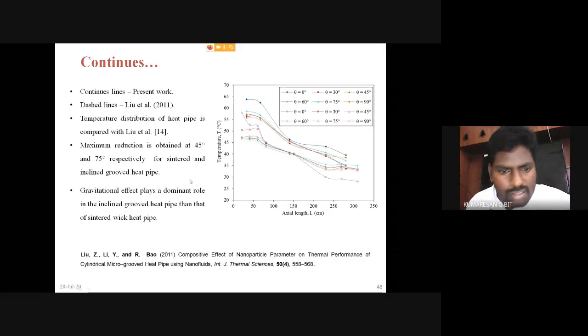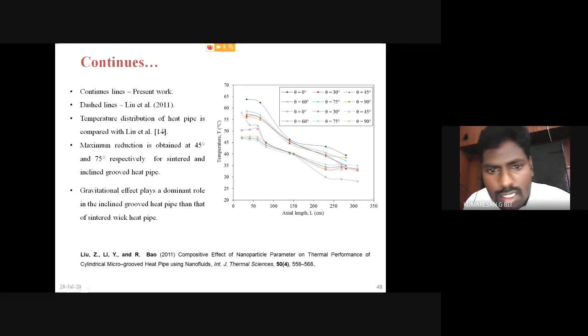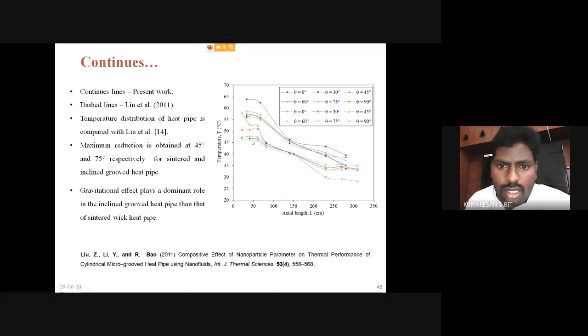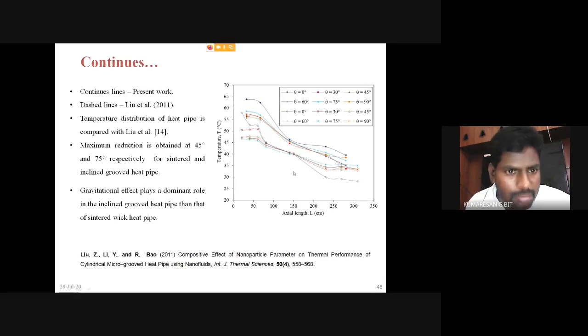Then next, the present study is compared with Liu et al. The surface temperature of the present study is compared with Liu et al. You see the trend formation of the surface temperature, and both have the same trend. Then the temperature distribution of the heat pipe is compared with Liu et al. The maximum reduction is obtained at 45 degree and 75 degree inclination for the sintered and the inclined grooved heat